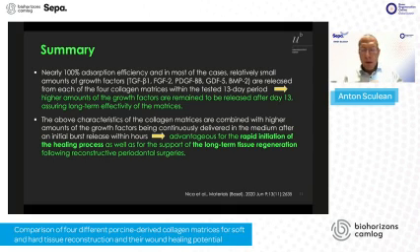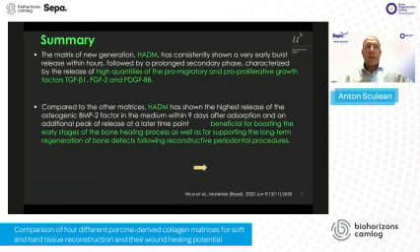However, some matrices seem to perform a little bit better than other matrices. If we look at the matrix of the new generation, namely the hydrated acellular dermal matrix, it has consistently shown a very high amount of proteins and protein release within hours, but it was followed by a prolonged secondary phase. This was characterized by release of high quantities of pro-migratory and pro-proliferative growth factors like TGF-beta1, FGF2, and